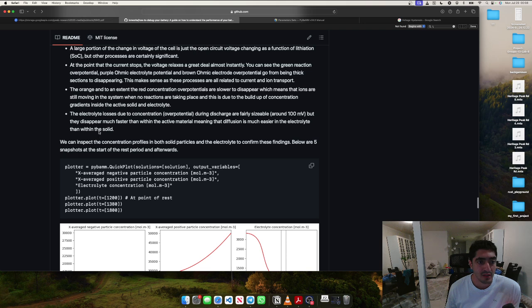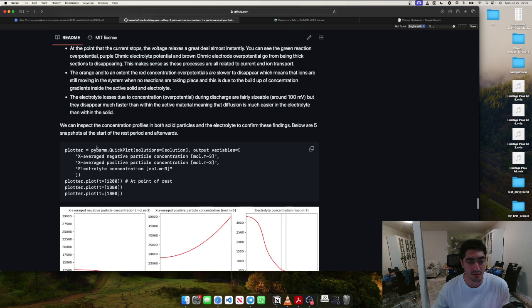The electrolyte losses due to concentration overpotential during discharge are fairly sizable, around 100 millivolts, but they disappear much faster than within the active material, meaning that diffusion is much easier in the electrolyte than within the solid. We can inspect the concentration profiles in both solid particles and the electrolyte to confirm these findings. Below are 5 snapshots at the start of the rest period and afterwards.